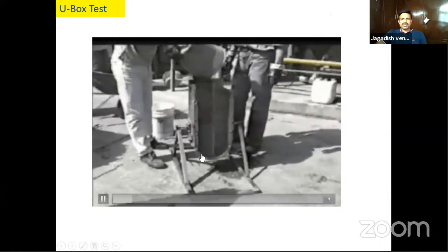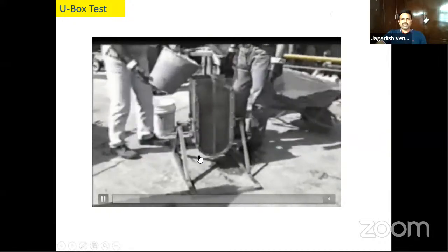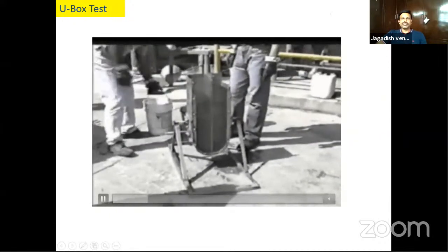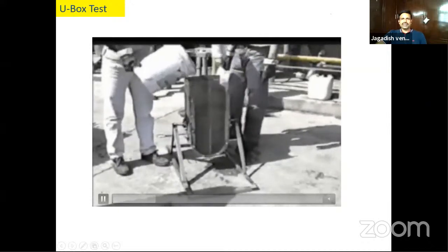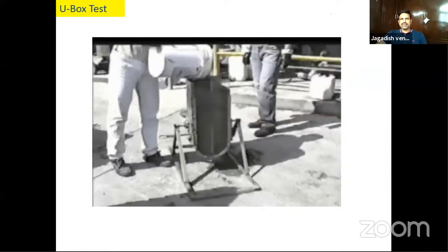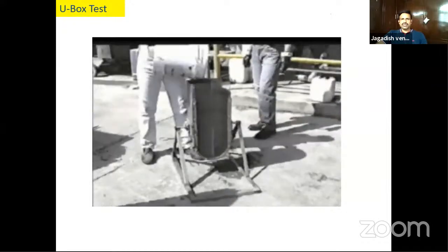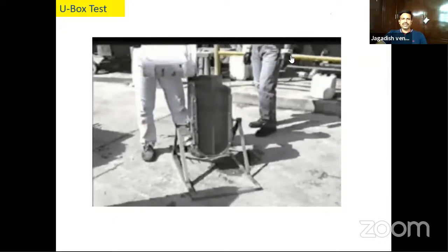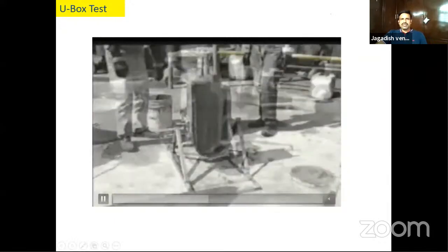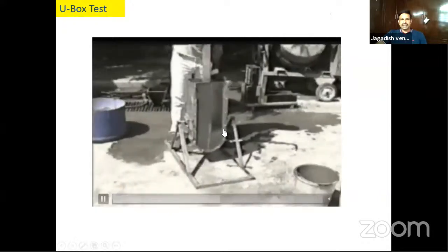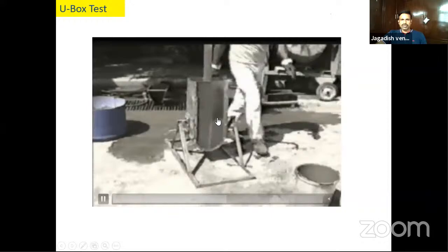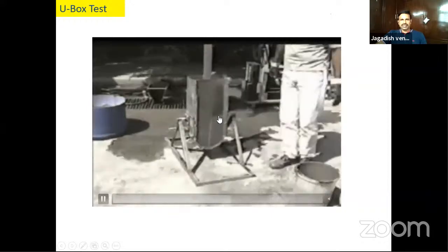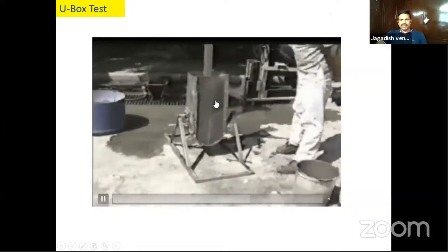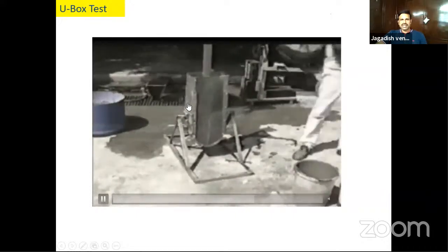So one of the limb, you are filling it using SCC. So while filling, the gate is closed. There is an obstruction between the one limb to another limb. Once you pour the SCC, you lift the gate, middle gate, you can see the concrete flow through the reinforcement and comes to the another limb. Then you measure the height difference between these two limbs. You can see here. So this is here and here. The height difference should be less than 30 mm.